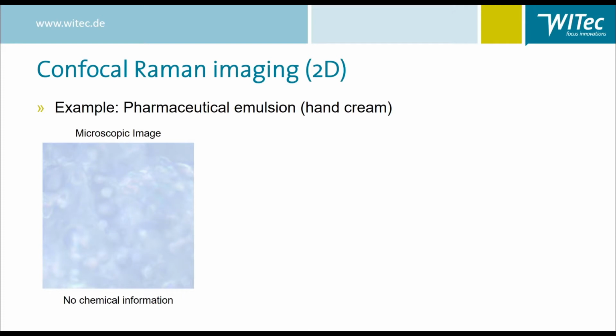In case you investigate bulky samples instead of powders, you will need two-dimensional Raman imaging in order to analyze the distribution of specific compounds or phases. So let me now show you how Raman images are measured. My example here is hand cream with a moisturizing ingredient. On the left, you see the bright field microscopic image in which we see some bubble-like structures, but yet we have no idea what these bubbles are.